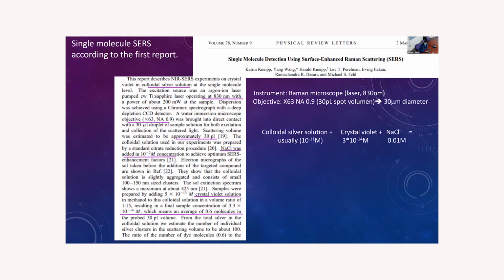Then the magic starts when they add a very high concentration of sodium chloride. So let's summarize. They are using a silver colloid solution. They add the analytes in a very low concentration, and they add this salt. So they are increasing the ionic force of the solution. That will make the colloid unstable and start to aggregate. And that's the point of this experiment.